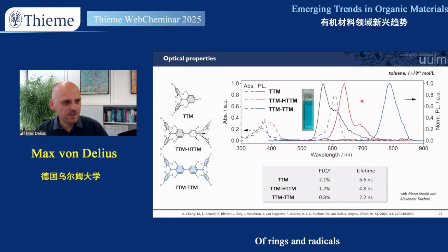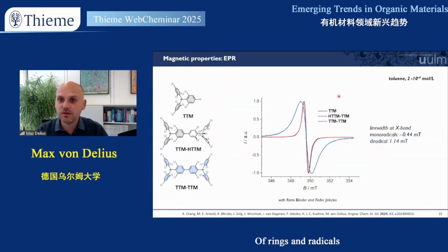The optical properties, just very briefly, are interesting too. We have this massive redshift emission in the NIR already. You see here almost 800 nanometers. The quantum yields are quite low, below 1%. So we're obviously working at increasing these. Compared to the simple monoradical, at least there's not a large drop to be seen here. So very interesting emission and absorption in a range that none of the other radicals or diradicals really occupy. So that can be something useful in the future.